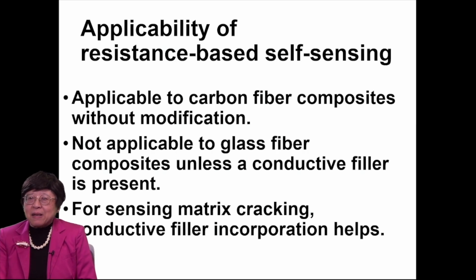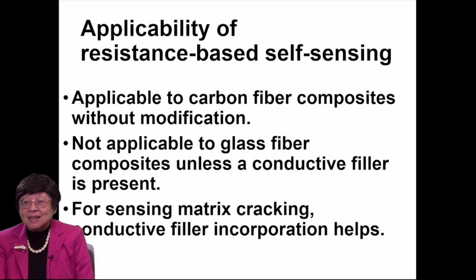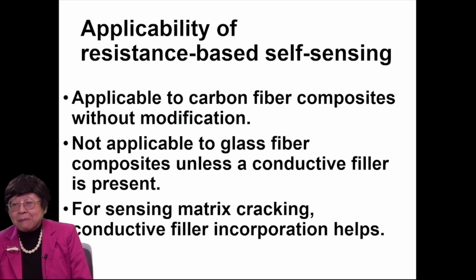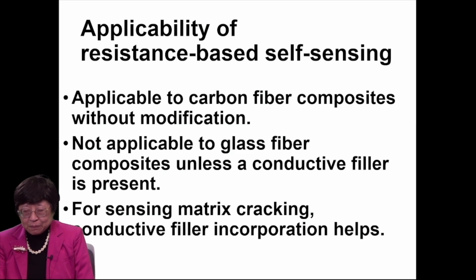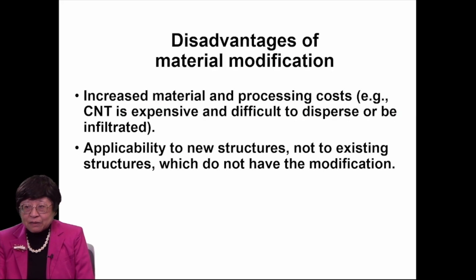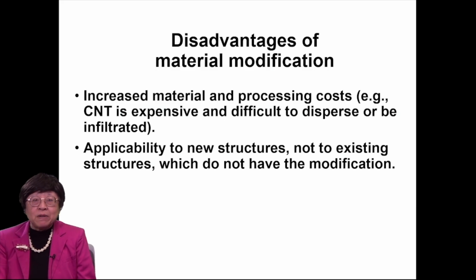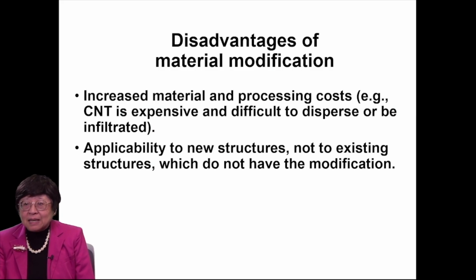The applicability of resistance-based self-sensing: this is applicable to carbon fiber composites without modification, but it's not applicable to glass fiber composites unless a conductive filler is present. For sensing matrix cracking, conductive filler incorporation helps. The disadvantages of material modification are the increased material and processing cost. For instance, carbon nanotube or CNT added is expensive, and also the CNT is difficult to disperse or be infiltrated. With material modification, the applicability is limited to new structures, not to existing structures which do not have the modification.